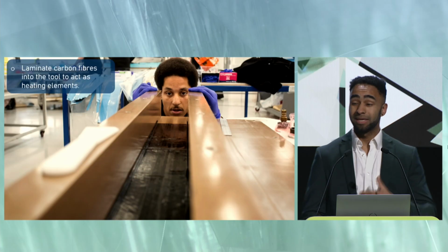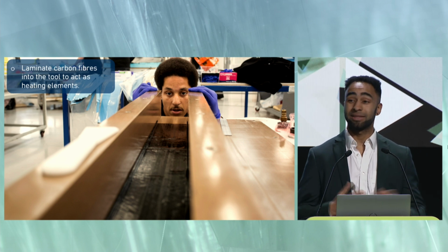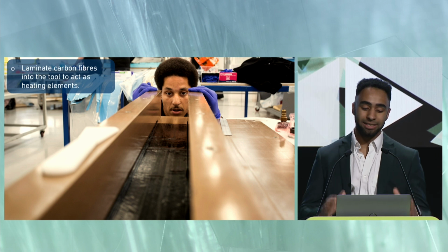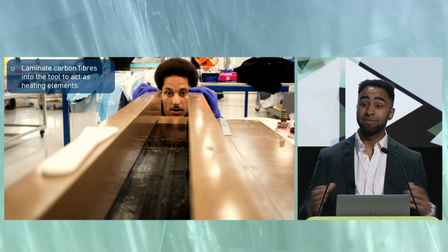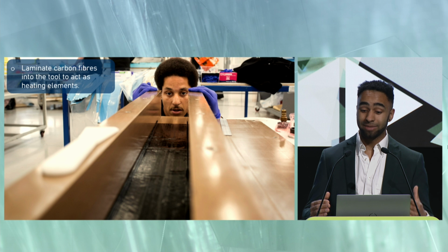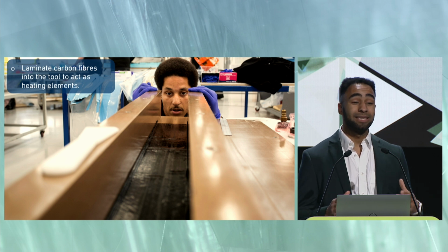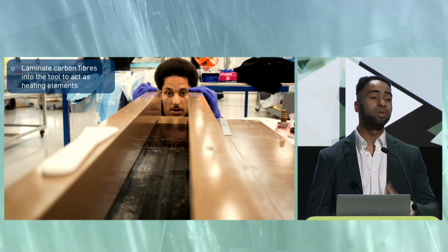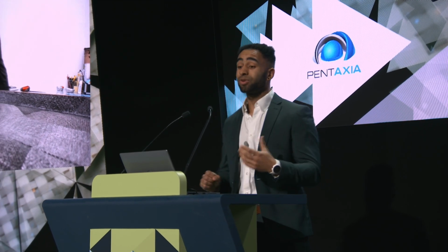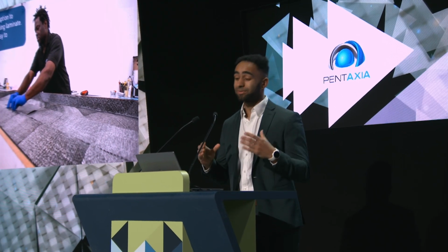So we've done something a little bit novel with the heater elements. Now, this is based off research from Matthew Conson on a project called the Maestro Project. And what it does is really utilizes the conductive capabilities of carbon fiber to be our heater element. So this is something that's never been done in tooling before, and it removes the design limitation of having to have thick or non-conforming heater elements in your composite tooling. And we see this as a push to the industry to try and incorporate more out-of-autoclave processes. It's only been a short program, but we've seen some really, really positive results from that.